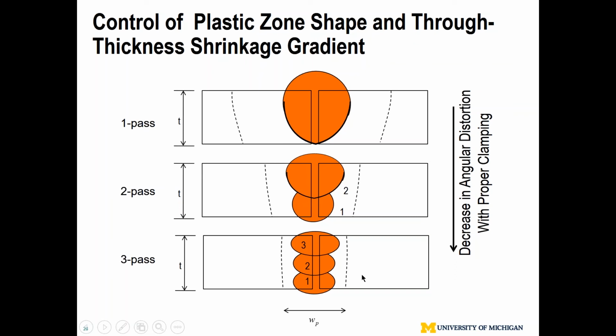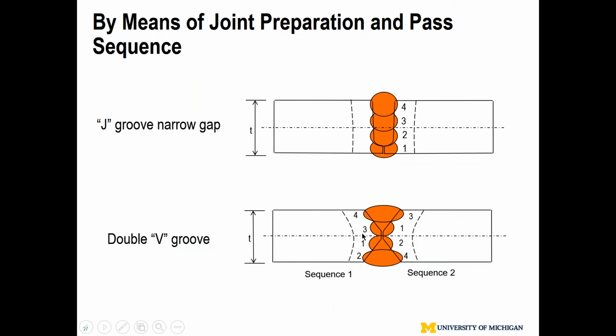Okay, so how do we maintain symmetry during deposition of pass one and pass two? When I deposit pass one, it's not symmetric. The plastic zone will be something like this. In that case, you use clamping to provide restraint, because you don't have symmetry, you need a fixture to control things, which we're going to get into later. And then once it's done and the plastic zone is symmetric, you can unclamp it and take it out of the fixture,